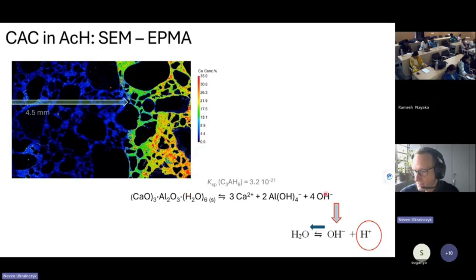Again, explained by the solubility constants. So you are increasing the dissolution of hydration products. Also, by acetic acid, you are complexating the calcium. You are making a calcium acetic complex, which is again taking calcium from the equilibrium ion activity product. So you need to dissolve even more. So this is why calcium aluminate, although it's a very acid resistant material, does not resist acetic acid so much.